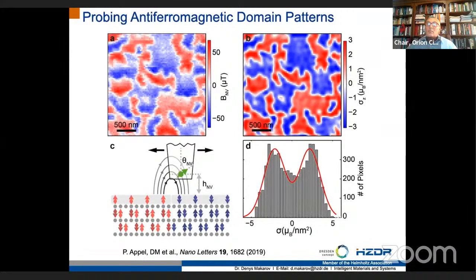What you can see is that domains are relatively large, a couple of hundreds of nanometers, which are substantially larger than the individual grain size, meaning that individual chromium oxide antiferromagnetic grains are exchange coupled to some extent to allow observing such kind of magnetic domain pattern.